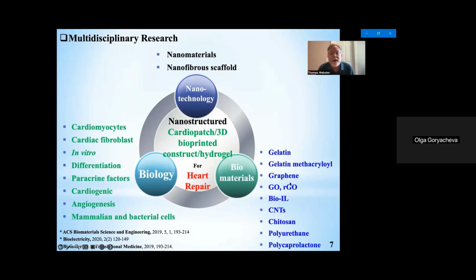Graphene has been our nanoparticle of choice. Carbon-based nanoparticles are very biocompatible. Graphene is conductive, easy, and inexpensive to add to these gel-like formulations. And in a composite form, you can distribute these nanoparticles, or in our case, some of the times we're using nanorods or carbon-based nanotubes, which can be distributed anisotropically to give heart tissue this anisotropic electrical and mechanical property.